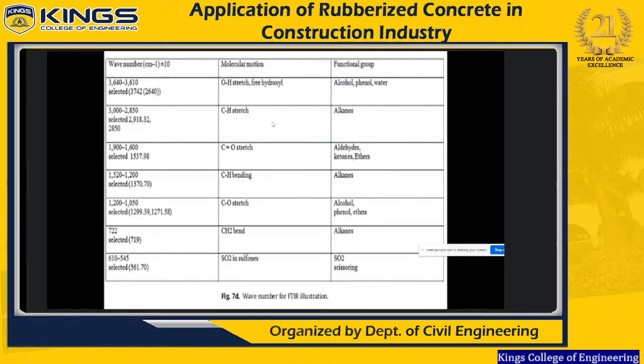So this is the wavelength for FTIR. We compare all the graphs for the control concrete here, then 3% non-treated, 6% non-treated rubber, 9% and so on. C2S means a silica component. Wherever you find it, it is there somewhere here. The dollar symbol is for SiO2. Wherever it is present, we are indicating which component is increasing or decreasing as we add the rubber, which we observed using this graph. This is a testing of specimen.